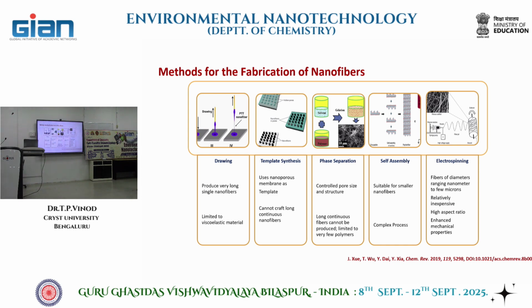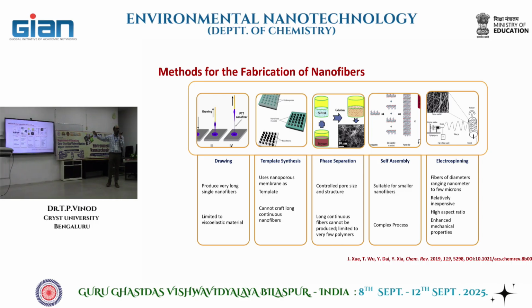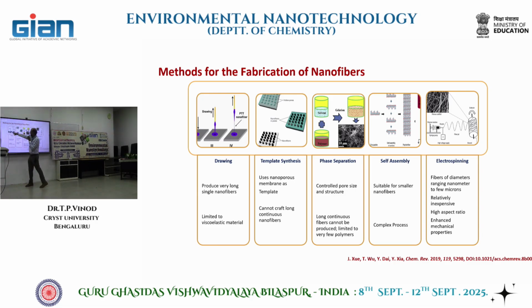When you compare other methods which are available for the formation of nanofibers, drawing is one method. Suppose you want to make an ultra long polymer fiber. What you do is you start with a polymer solution, come up with a needle, touch it there, and then pull it as long as you can. It will elongate in the form of a nanofiber. If you elongate enough, you get a diameter in the nanoscale dimension. The advantage is you can have very, very long fibers. The disadvantage is it's very difficult to scale up, right?